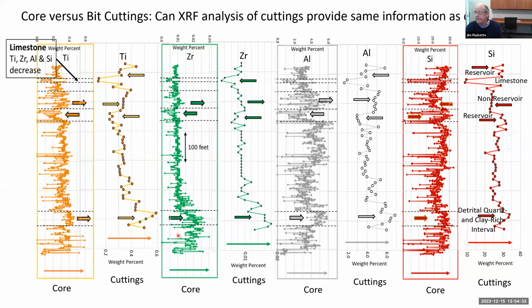But when we get down to that thicker interval, that detrital quartz and clay rich interval, we see our titanium increasing with the core values. We see the zirconium increasing. Yeah, it's dropped down a little bit because of the lag issue. We see the aluminum increasing, and we see the silicon increasing.